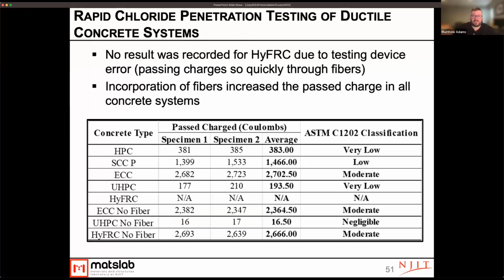early age. So one thing that we looked at was whether using the fibers in these mixtures would impact the test method. Because remember, this test method is not actually passing chlorides through the system, it's just passing charge. Electrons are much smaller than full chloride ions, and so it's just a surrogate test, it's not an exact measurement. While that relationship has been established quite well with ordinary concrete, so it's a great test to use on the HPC and SCC mixtures, for our systems with fibers, it may not actually work well. Also, the cementitious microstructural system is different.